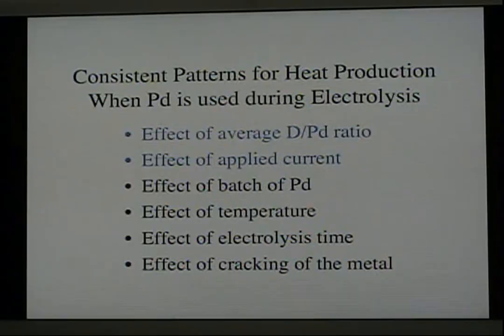There's also an effect of temperature. The higher the temperature, the more heat's produced. That's been found in ordinary D2O electrolytic action, but also in fused salt, which I'll show you. The effect of electrolysis time is important. It takes a while for the proper conditions to be created to generate excess energy. And that electrolysis time is a critical aspect of this phenomenon that many people have ignored in the past.